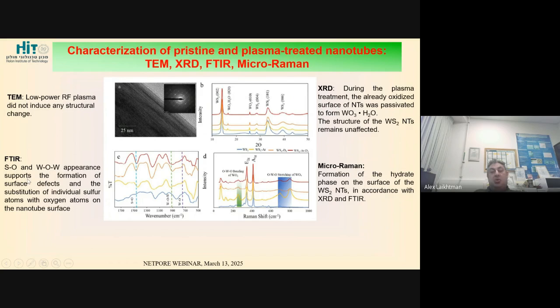But where are the changes? There are some chemical changes. So we can observe by FTIR, for example, that there is formation of some bonds with oxygen, sulfur, and tungsten oxygen. So this supports our assumption about the formation of surface defects and substitution of very individual sulfur atoms with oxygen atoms. So we don't produce layers of oxide, but just individual sites.